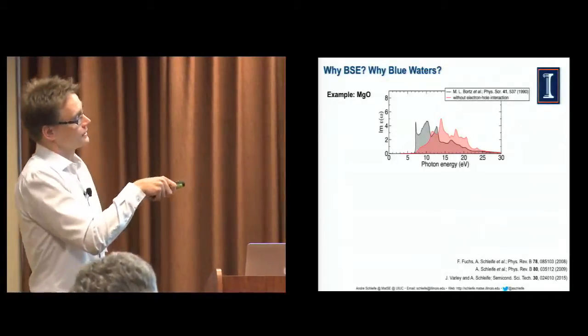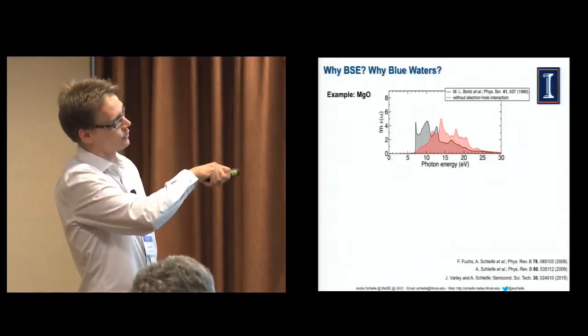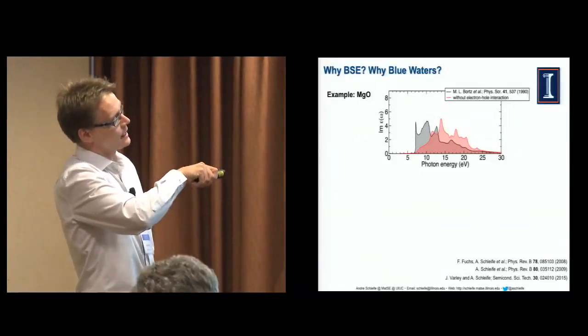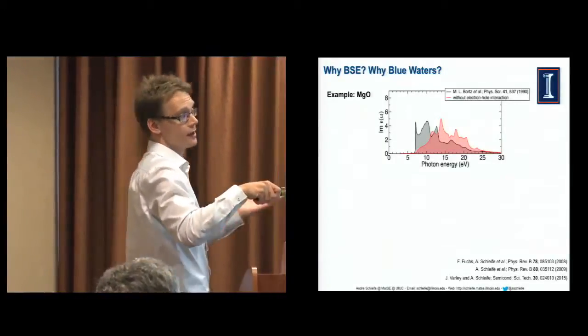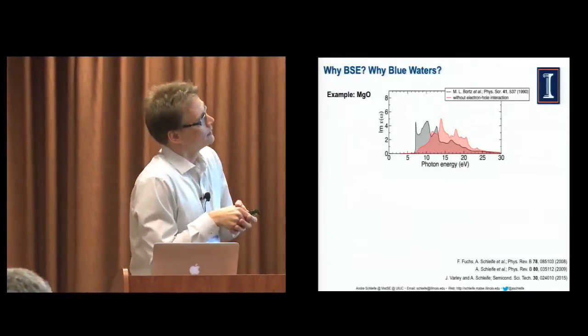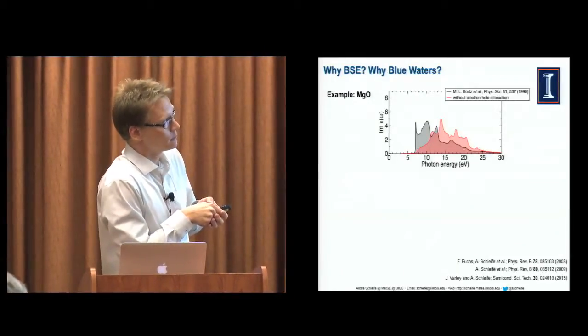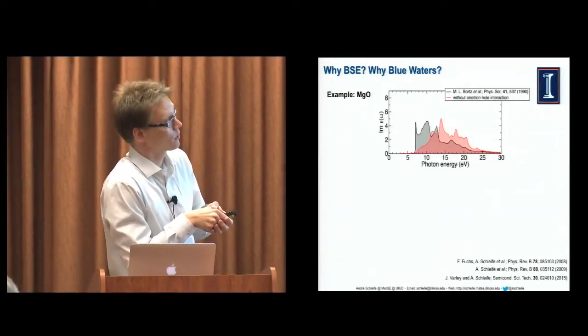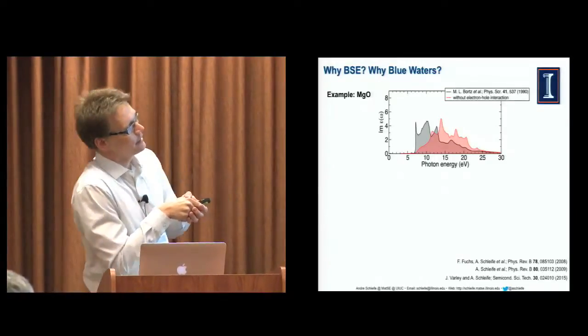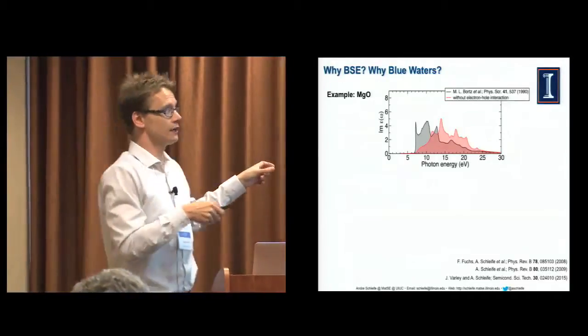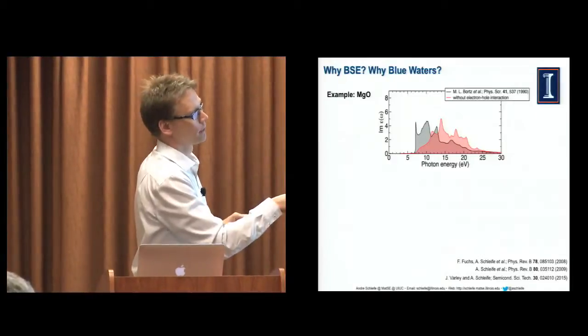Okay, so what you can see here is this dielectric function that I just talked about in the previous slide on the y-axis, and the x-axis is the photon energy, right? The energy of the incoming light. So we have two curves here. The black one is experiment for magnesium oxide that will look like this curve. Now, if we did this HSE calculations I mentioned earlier, we would get something like the red curve, right?